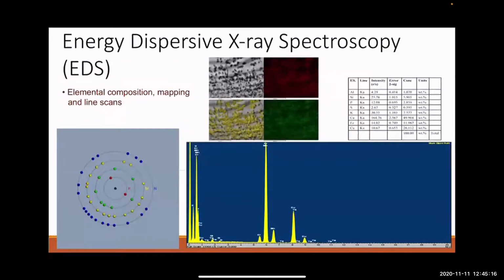Another thing you can do, since you're irradiating the sample with electrons, and typically you're looking at the electrons that scatter or don't scatter out of your sample, but some electrons also excite X-rays. So if you look at this little movie here, your primary beam comes in on your conventional atomic model, and you can knock out electrons in their orbitals, and electrons in higher energy states can drop down. As they do so, they can emit X-rays.